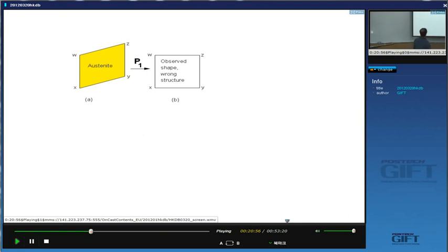Now, if I now shear it on this plane, okay, on the horizontal plane, then the combination of two shears leaves a single line unchanged, right? Because every line on this plane is unchanged by this shear, every line on this plane is unchanged by this shear. So if I have two shears, then there's only a single line left. So the combination of two shears on different planes is an invariant line strain. Okay, so I'm going to do that.